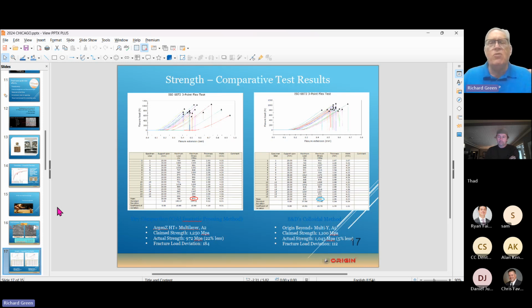And that's a great thing to have for your sintering overall. But if you're going to be doing the 1 hour sintering, the time in the oven is only about 40 minutes at high temp. And so if you test it for an hour, your oven's going to be off. And so Daniel, one of our owners here, has devised a process where you can set up the cycle, run the TCR, measure it out, and make sure that the temperature we've got in the muffle is the correct temperature to